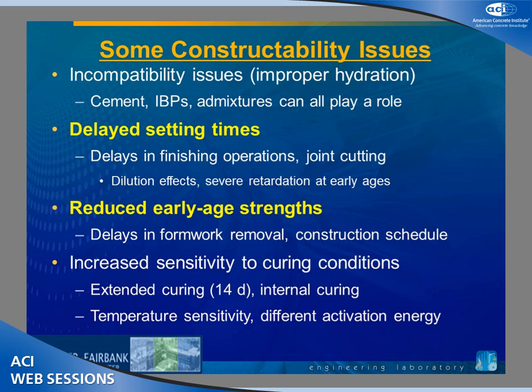constructibility issue can be the increased sensitivity to curing conditions. I've heard some mixed conclusions on this here at this meeting as to whether fly ash concretes need longer curing times or not. But the general consensus, I think, among state DOTs in particular, is that you do need to do extended curing, maybe 14-day curing. Jason Weiss was talking about internal curing this morning for these high-volume fly ash mixtures.